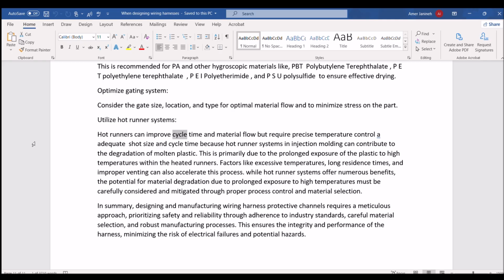Hot runners can improve cycle time and material flow but require precise temperature control, adequate shot size and cycle time, because hot runner systems in injection molding can contribute to the degradation of molten plastic. This is primarily due to the prolonged exposure of the plastic to high temperatures within the heated runners. Factors like excessive temperatures, long residence times, and improper venting can also accelerate this process. While hot runner systems offer numerous benefits, the potential for material degradation due to prolonged exposure to high temperatures must be carefully considered and mitigated through proper process control and material selection.